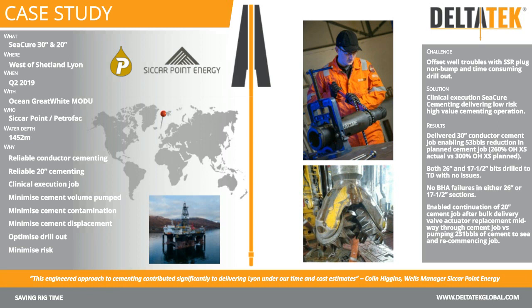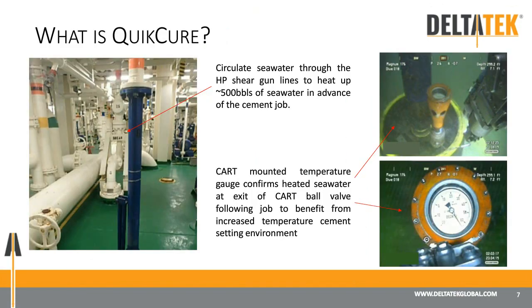Yeah, good question. So in the 6 deployments of QuickCure that we've done so far, what we've experienced, from a surface starting temperature of 65 degrees C, has been quite incredible: in 300 feet of water, over 60 degrees C coming out of the cart ball valve. Now, the original modeling that was done indicated that it would probably be a lot lower than this. However, if I flip back to slide 7 here, we can see from the captured ROV footage in the bottom right-hand corner, the ROV camera witnessing over 60 degrees C on the gauge there from a starting temperature of 65 degrees C.